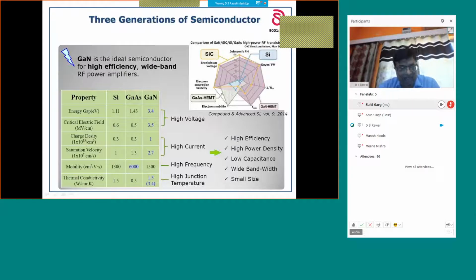And then another important material parameter for these high power, high frequency applications is the thermal conductivity. So the thermal conductivity of gallium nitride is of the order of silicon only, but since there is no native substrate for this, it is grown on foreign substrates, and silicon carbide is the most suitable substrate for GaN HEMT devices.